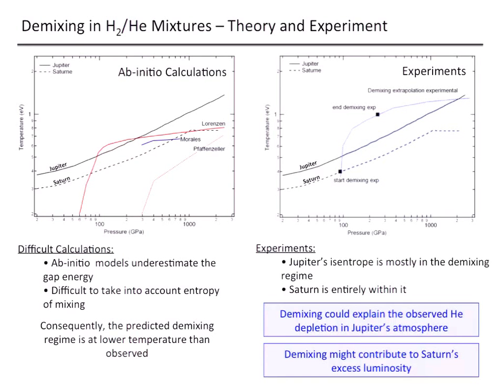These are difficult things to take into account in calculations, which is why the experiments are valuable here. What we conclude is that most of Jupiter's isentrope actually falls within this demixing region, and Saturn's almost entirely within it. This might contribute partly to Saturn's excess luminosity, and could also possibly explain why we see less helium in Jupiter's atmosphere than expected.